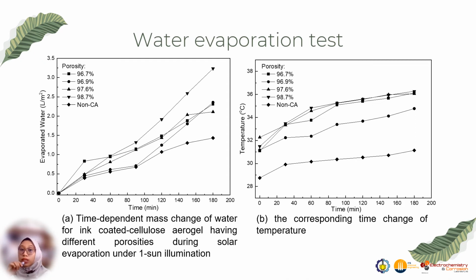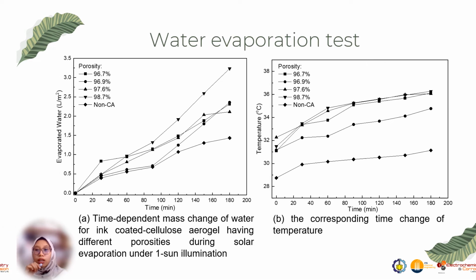It is clear that the porosity has a great effect on the evaporation rate. This may be related to the capability of aerogel to capillary pump the water from the reservoir below the aerogel. As discussed before, the pumping capacity increased with an increase in porosity, and the highest pumping capacity was obtained at porosity of 98.7%. In addition, it may also be related to the thermal conductivity of the aerogel, which serves as thermal insulator to avoid heat loss.